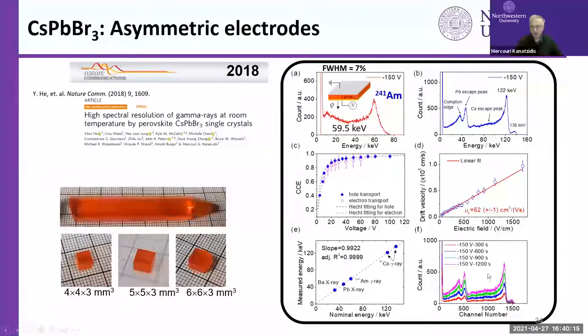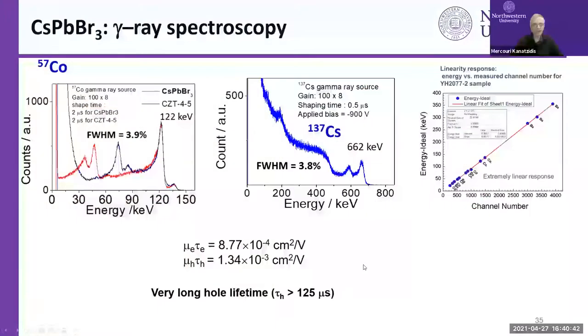These are the spectra here as a function of time. We're counting for 30 seconds, 60 seconds, and so on. We get more and more counts. And this is the dependence of the nominal energy of the gamma ray sources, like americium, cobalt, and other sources, versus the measured energy, and we see a very nice, beautiful linear dependence. And that's what you want to see.